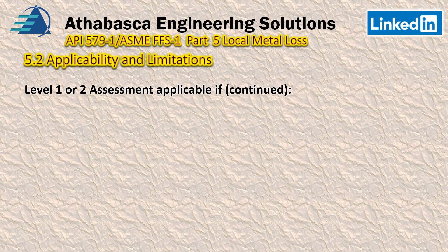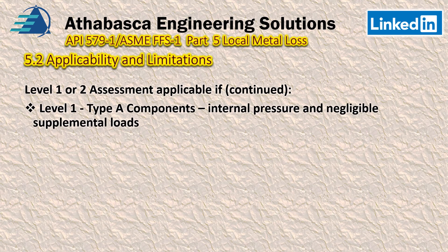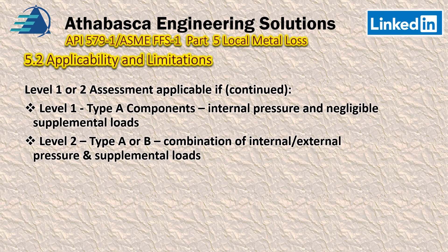For Level 1 and 2 assessments: Level 1 is applicable to Type A components — a reminder that these are components with internal pressure but negligible supplemental loads like bending. Level 2 can be used for Type A or B parts, where you have a combination of internal or external pressure and supplemental loads. Refer to the previous videos on component types for more detail.